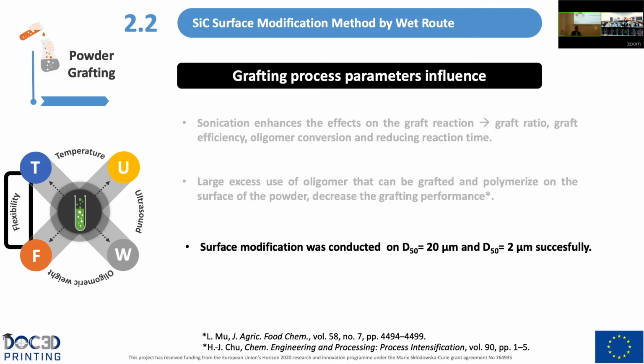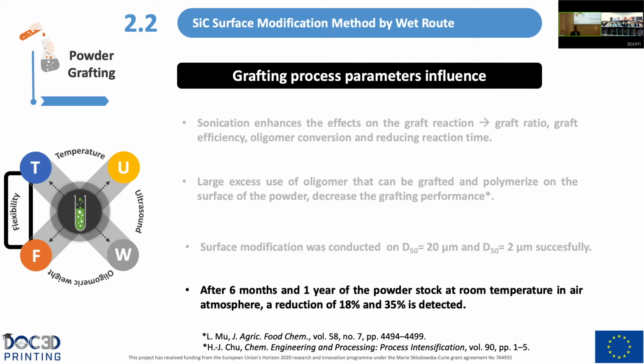And regarding the flexibility of the process, we have conducted a surface modification of 2 different silicon carbide powders, 20 micrometers and 2 micrometers. And finally, after 6 months and 1 year of powder stock at room temperature in air atmosphere, a reduction of 18% and 35% is detected in the grafting efficiency.